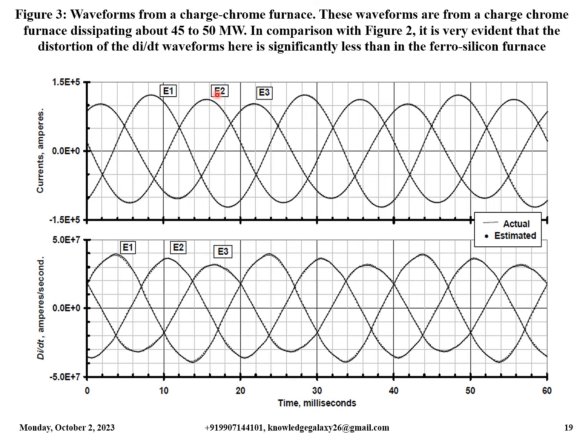And this is figure 3, waveforms from a charge-chrome furnace. These waveforms are from a charge-chrome furnace dissipating about 45 to 50 megawatt. In comparison with figure 2, it is very evident that the distortion of the di by dt waveforms here is significantly less than in the ferrosilicon furnace. I have already explained this. I hope it is very much clear to you all.